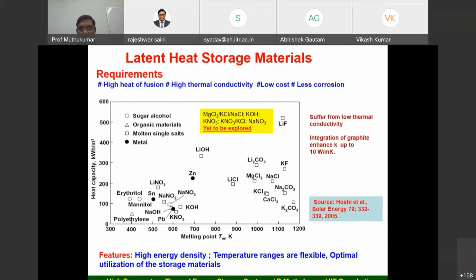But basically, coming to the important characteristics required, this material should have high heat of fusion, that is very important, high thermal conductivity, and low corrosion, because most of the PCMs are highly corrosive. If you go for the nitrate or the potassium-based or the carbonate-based salts, they are highly corrosive in nature. So you have to go for nickel-coated stainless steel, or high corrosion resistance steel. Obviously this will increase the cost of the heat exchanger, but we have no other option. We have to go for it. Otherwise, the PCM will sooner or later eat away the heat exchanger material.